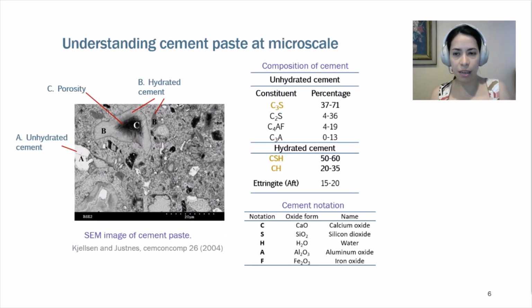And here you can see an SEM image of cement paste. And you see here the three main components I talked about: unhydrated cement, porosity, and hydrated cement. So if we go for the unhydrated, and I'm going to be talking a lot about C3S, which is not related to carbon. I'm using here civil engineering notation, where C is calcium oxide and S is silicon dioxide. So you have C3S and C2S, tricalcium silicate and dicalcium silicate, that are the largest components, accounting for more than 70%. Now, when they react with water, and again, they react partially, we have CSH, or calcium silicate hydrate. This accounts for more than 60% of the total material at the end in the mixture, and it is the matrix, the main component of cement paste.